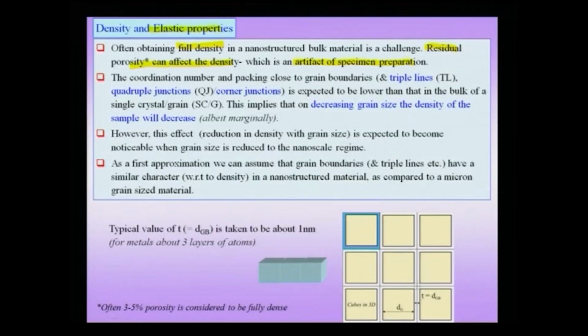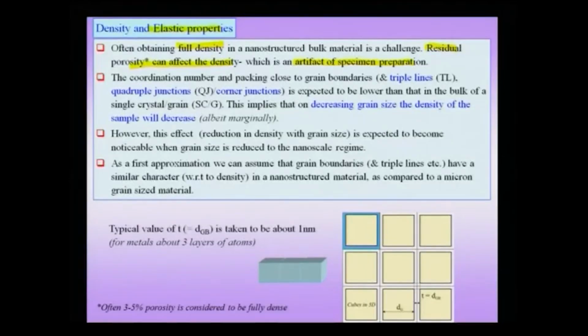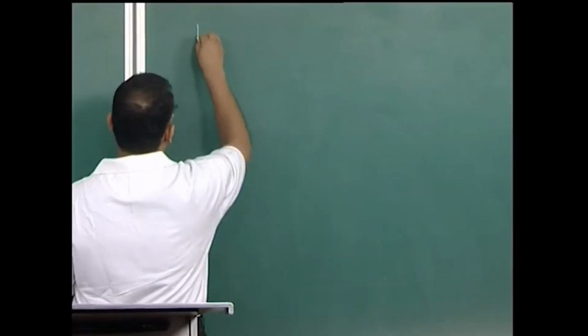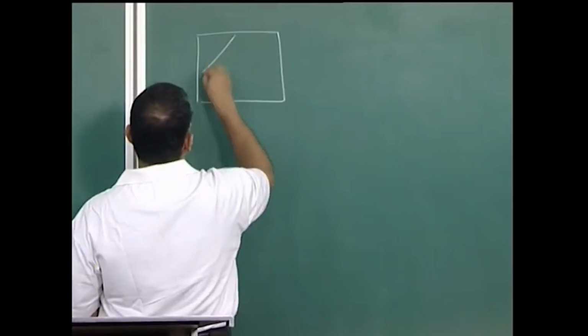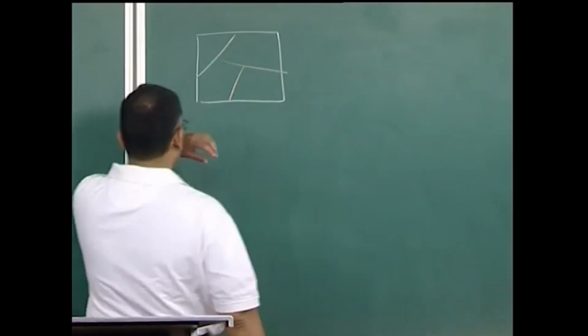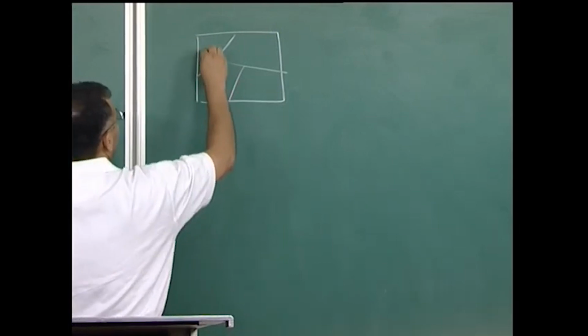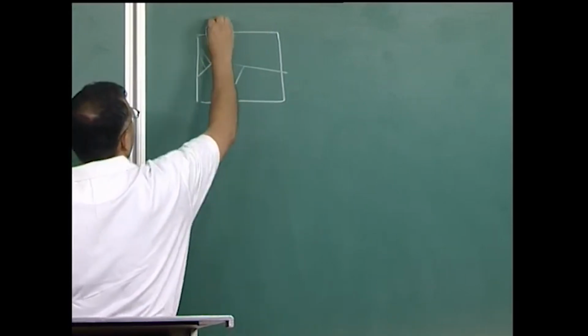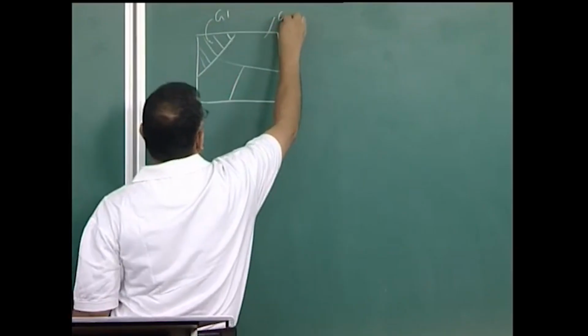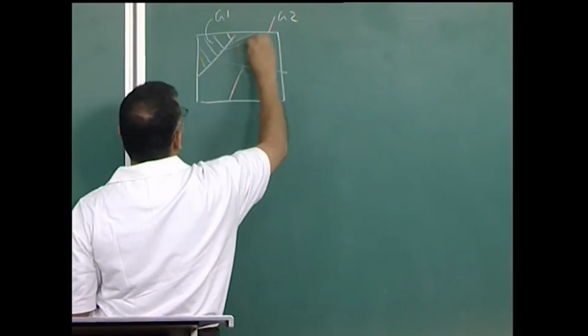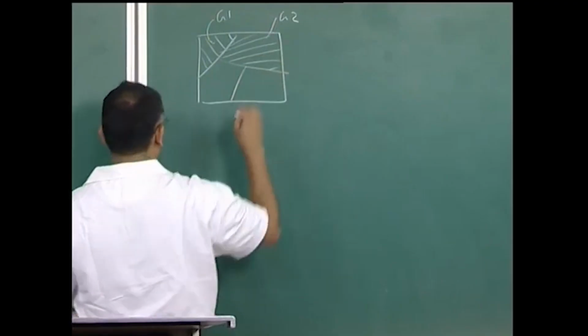Now, before we take up the elastic properties of a nanocrystal, it is important to note what is a grain, what is a grain boundary, and what are the higher order entities in a grain structure. Now, I can visualize that of course, you have a single crystal, then you have only one defect in the material, which is a surface. Suppose I have a multiple grain material and I draw it schematically here, then I can notice that each one of these is a grain, and one grain can be differentiated from another. So, this is grain 1 and this is grain 2, and one is differentiated from the other by the orientation difference across the grain boundary.